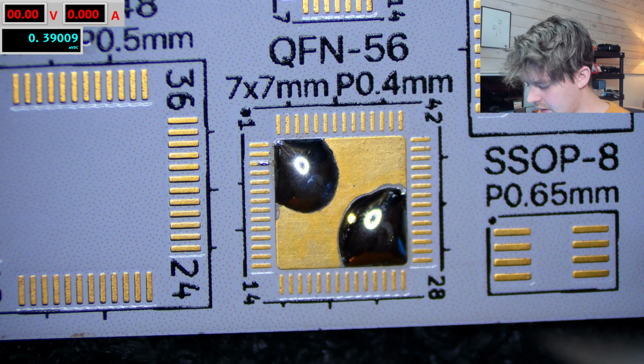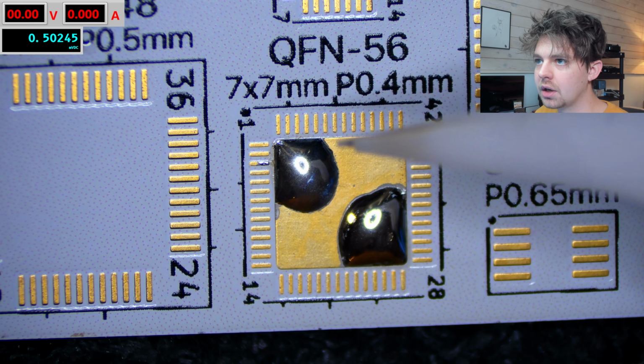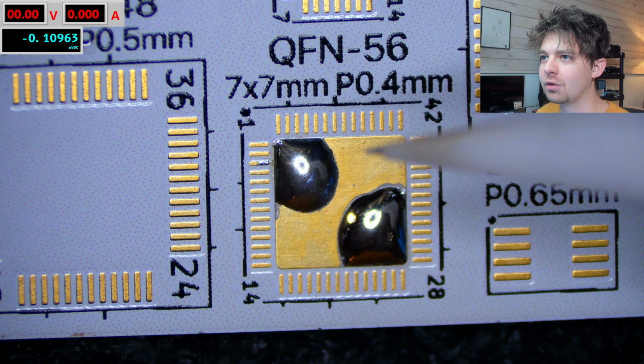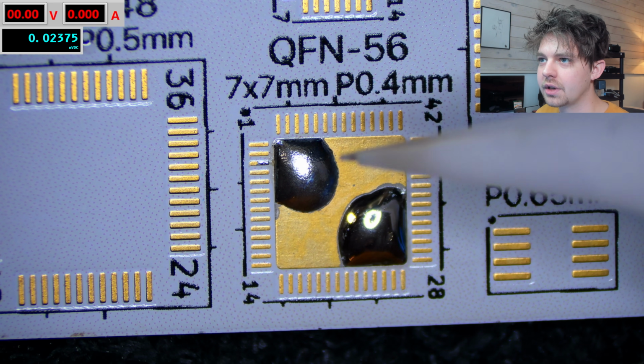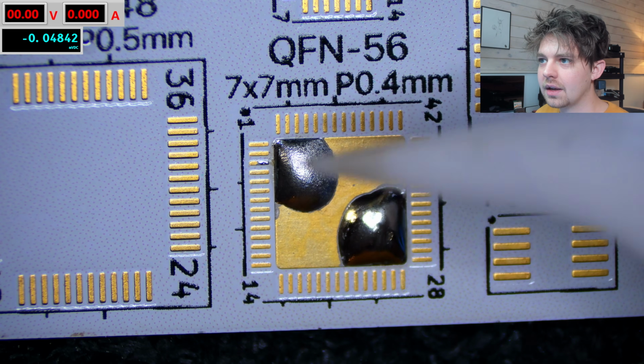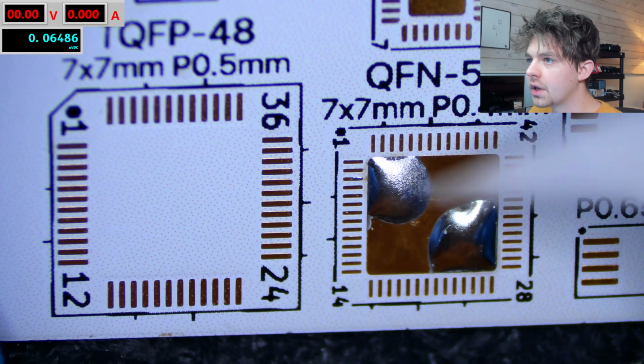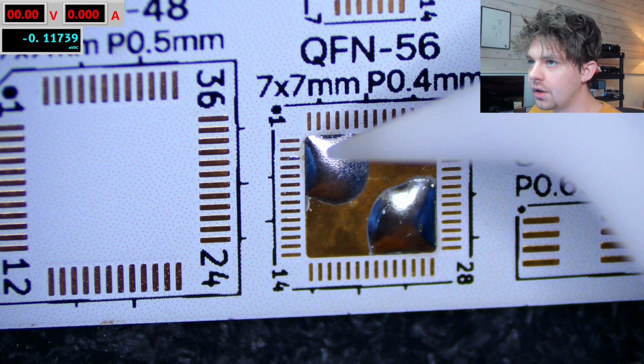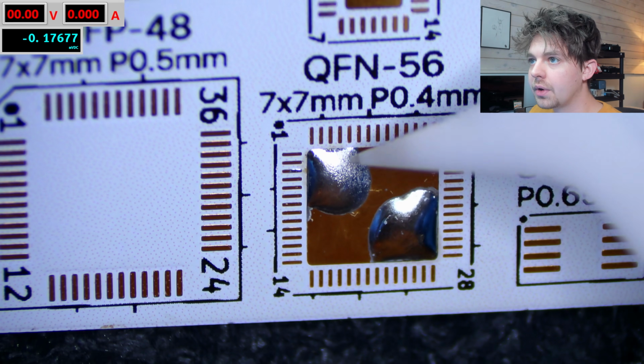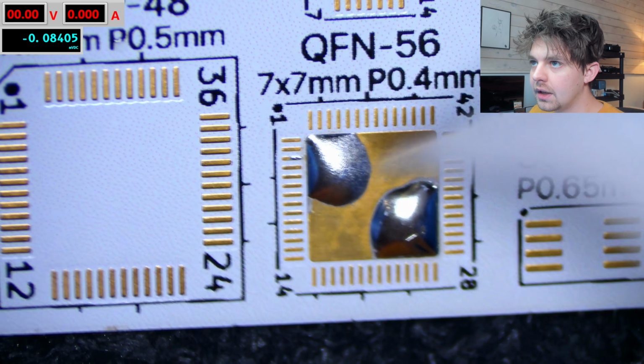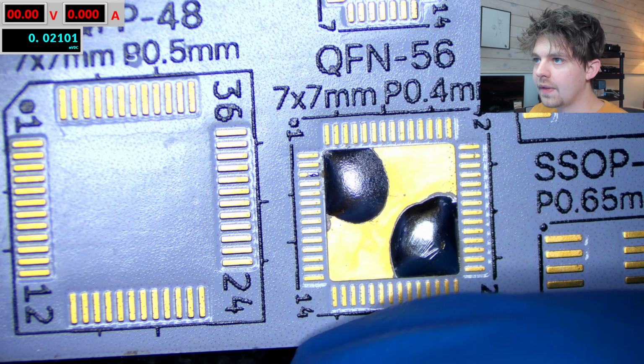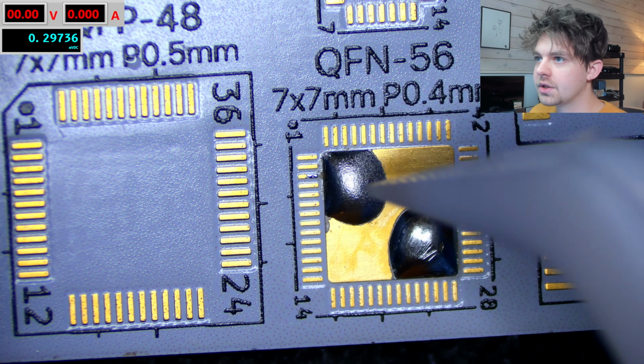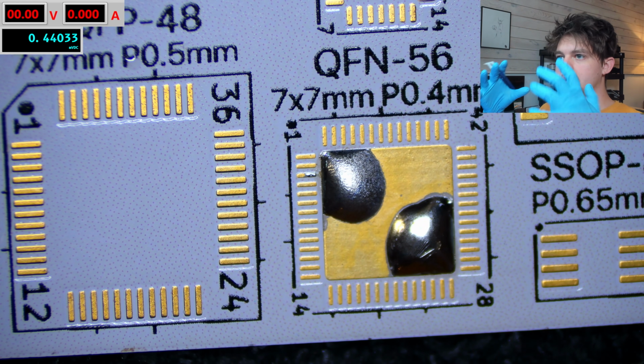So the 60-40 should look a little bit weird, for lack of a better word, as it starts to solidify. There you go, you can see that compared to this. So I'm just going to refer to these as eutectic and non-eutectic. For the non-eutectic one, you can see it is very grainy. It's solidified in a bit of a weird way. That's because during that plastic range, some of the solder was moving around while it was solidifying, and it creates this weird, gross texture.